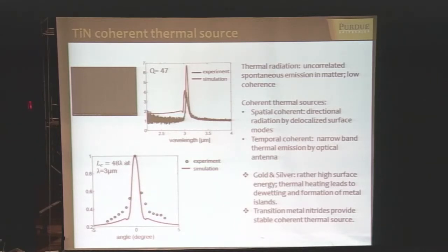However, if you structure it as shown here, in this particular case we designed it so that because of propagating surface waves, it's highly directional emission—which means you have high spatial coherence. You see that the width of the angular distribution is around 1 degree only.